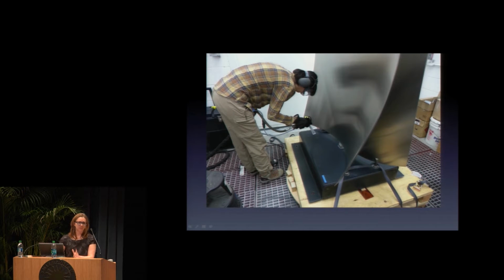I also use it just as surface prep, not to remove paint. So this is a sculpture by Robert Adams that has a mild steel base painted with polyurethane. And periodically, it just needs to be repainted. People step on it all the time. And rather than having to fully strip and repaint, I can just sand down the surface a little bit and then use the carbon dioxide blasting as a surface prep prior to adding another coat.